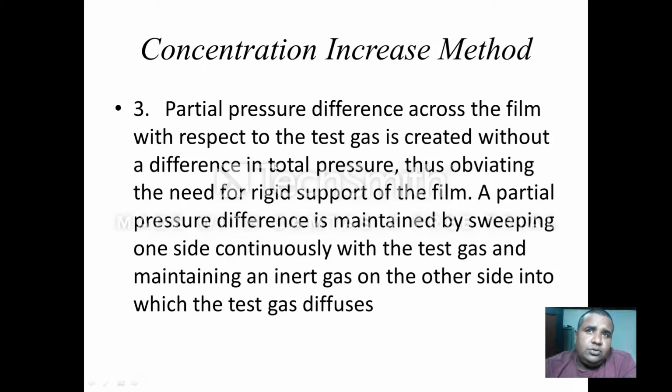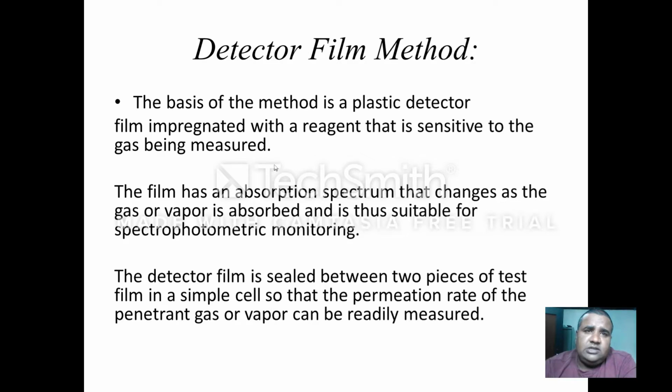Okay, so replacing it with another gas, there is a diffusion of the test gas from the high concentration to the low concentration zone, and finally that concentration can be determined by gas chromatography or any thermal imaging or thermal scanning devices. So this is the concentration increase method.